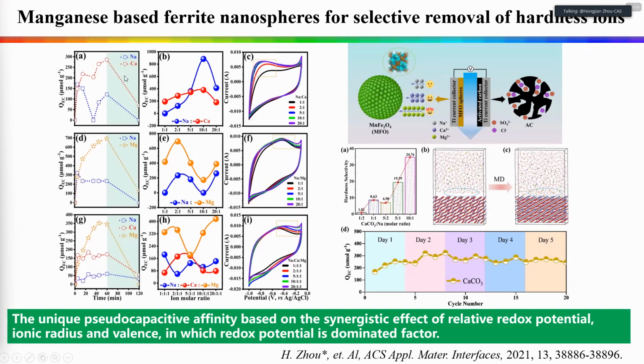By using the electrochemical characterization, we find the unique pseudocapacitive affinity is based on the synergistic effect of relative redox potential, and also the ionic radius and valence, but the redox potential is the dominant factor. And also this material, we tried running for 5 days the hardness treatment. Our material shows good stability.